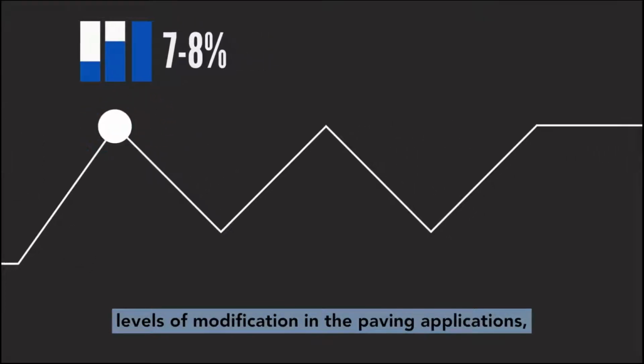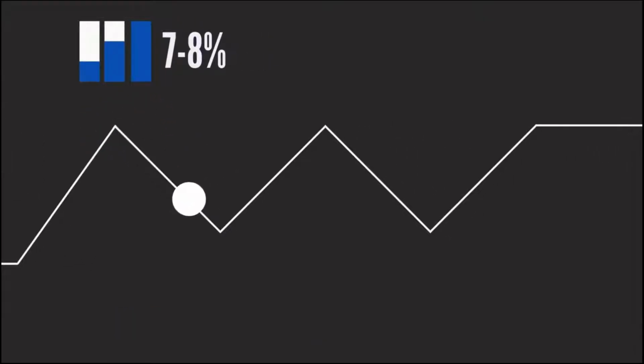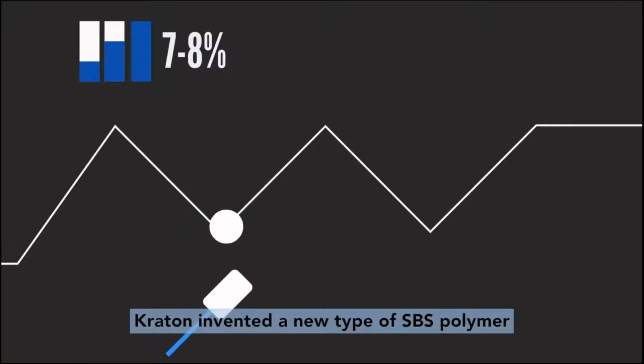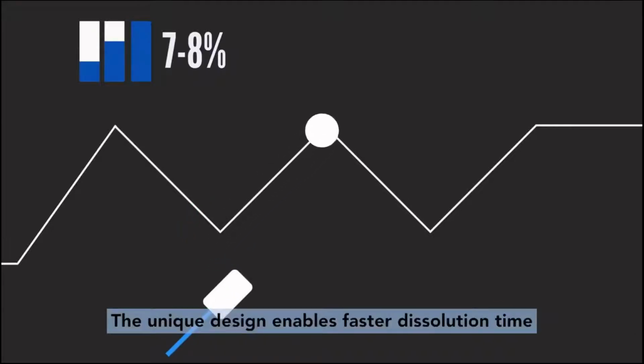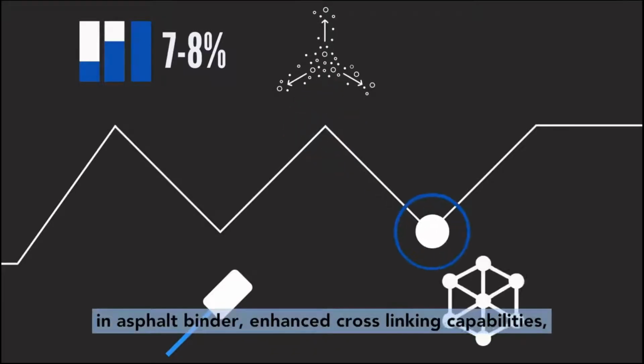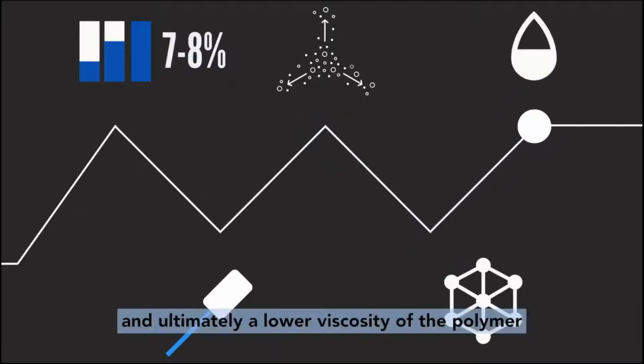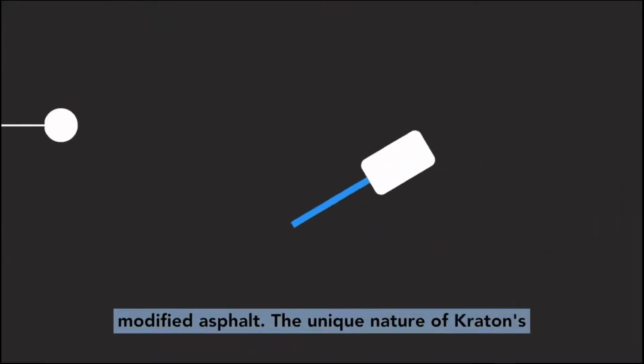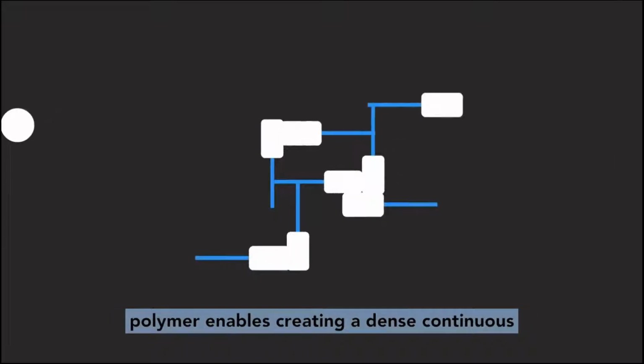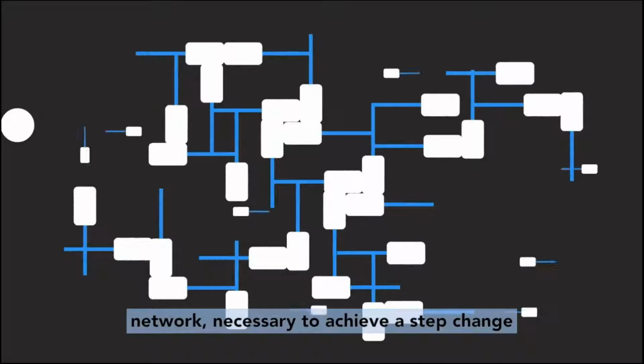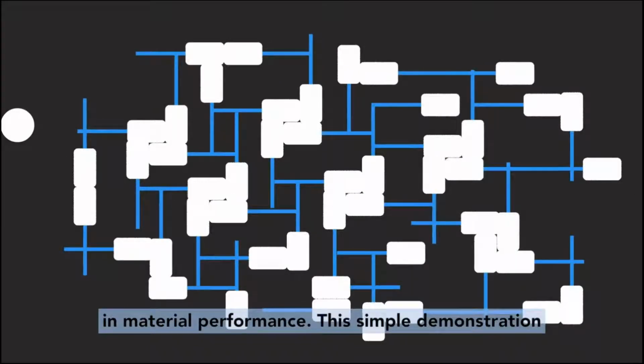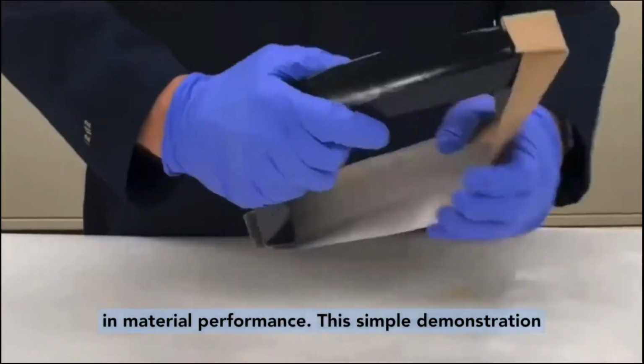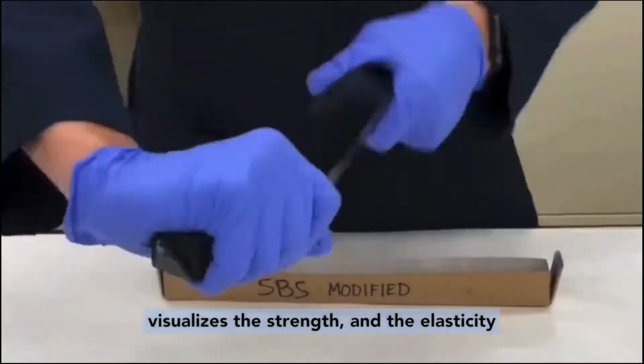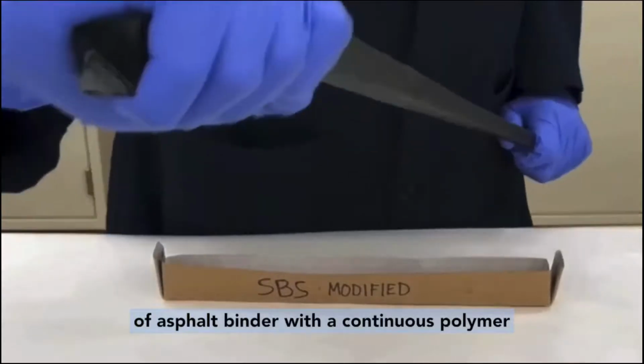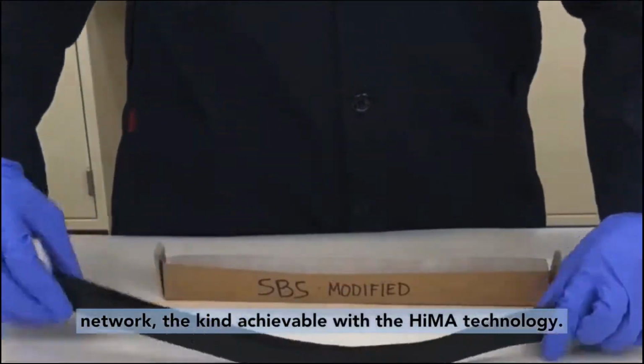To enable the high levels of modification in the paving applications, Kraton invented a new type of SBS polymer. The unique design enabled faster dissolution time in asphalt binder, enhanced cross-linking capabilities, and ultimately a lower viscosity of the polymer modified asphalt. The unique nature of Kraton's polymer enables creating a dense continuous network necessary to achieve a step change in material performance. This simple demonstration visualizes the strength and the elasticity of asphalt binder with a continuous polymer network, the kind achievable with the HiMA technology.